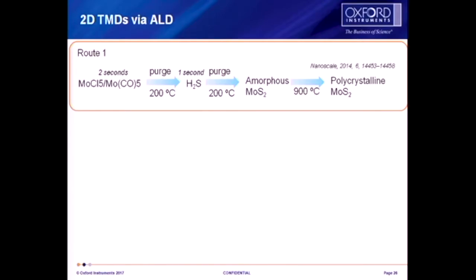You could put down a very thin layer of molybdenum, one second purge, you get amorphous molybdenum disulfide, then you take it out and do a post anneal to get a polycrystalline material. But that's taking you back up to 900 degrees C, so why not just grow it thermally? So it's not actually giving us any real advantages.